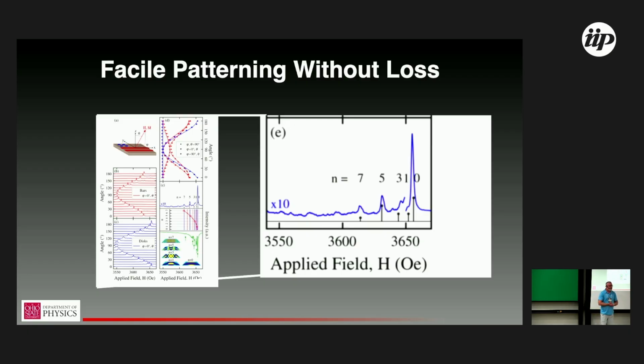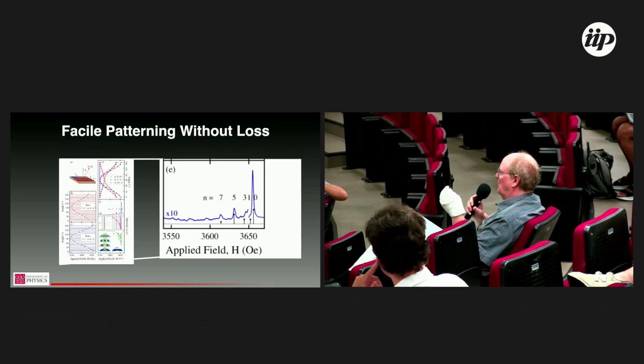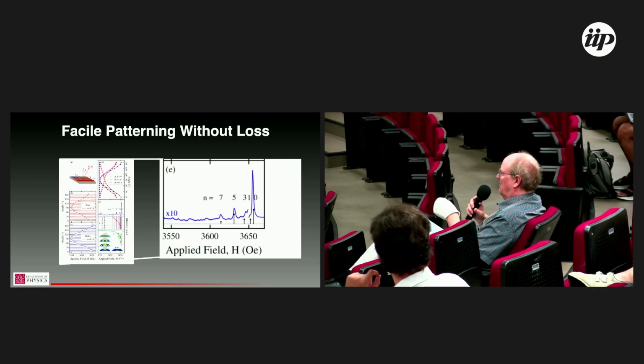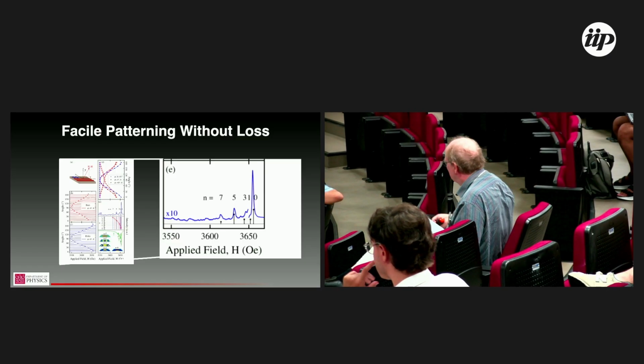Yeah, Georg. I would simply like to add an interesting thought at that point, because it's actually a trade-off when you make the structure smaller. It has to do with the inhomogeneous broadening. So depending on the material, for YIG, if you can make the structure small without reducing the internal damping or the magnetic quality, then the smallest structures actually give you the best line width, because the inhomogeneous broadening is much smaller. So you have to see how small you can get without reducing the quality, and then you have a good bet that this will give you the smallest line width. Yep, that's an excellent point.